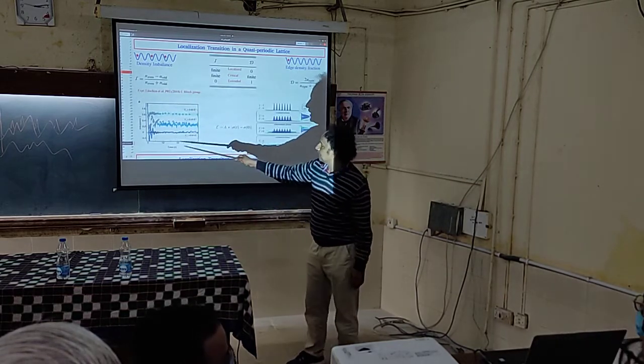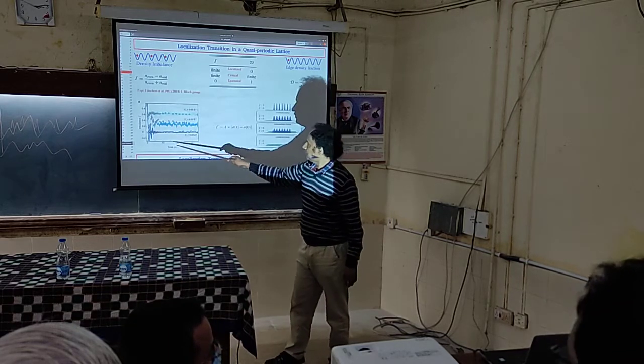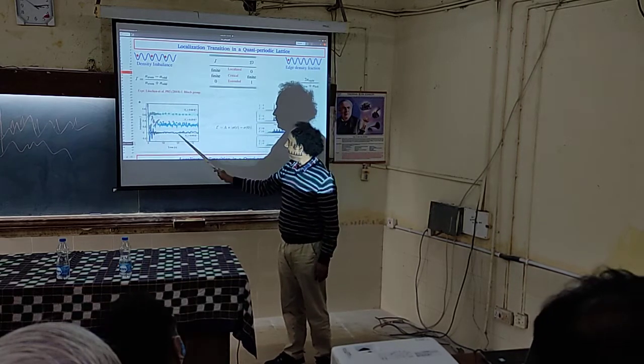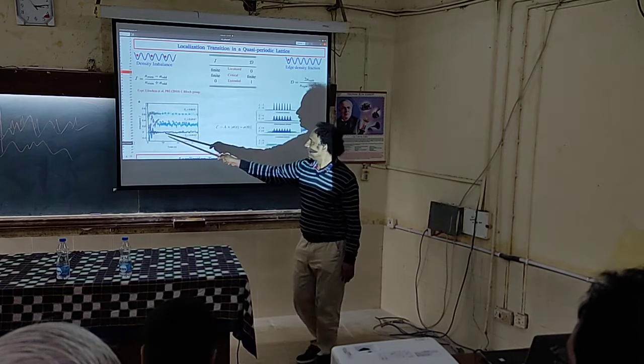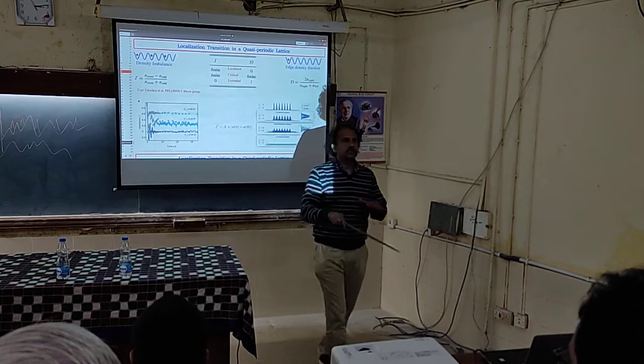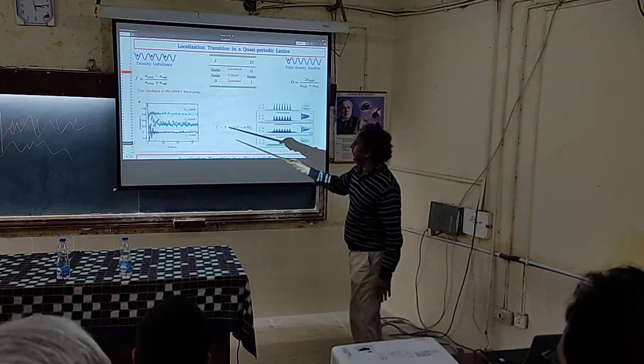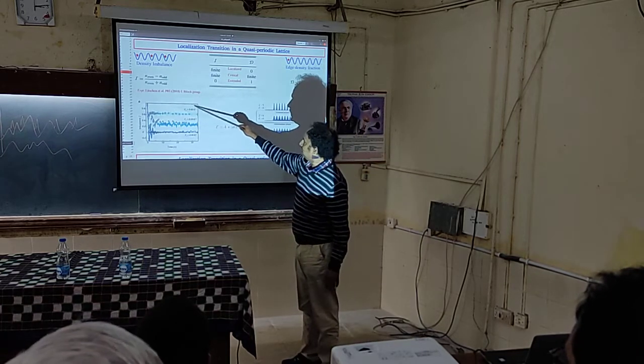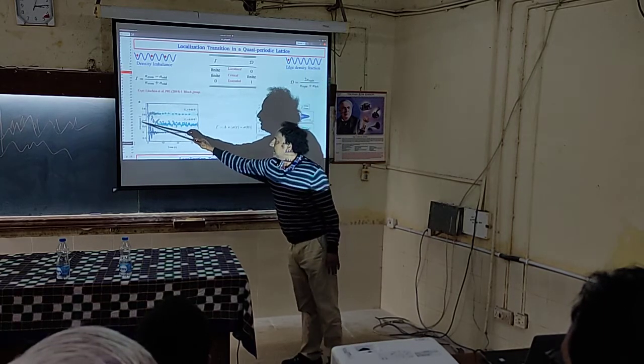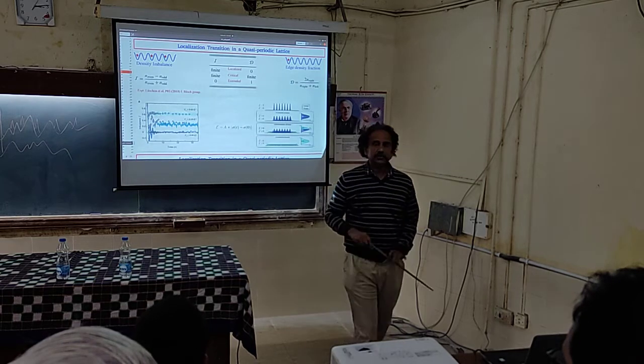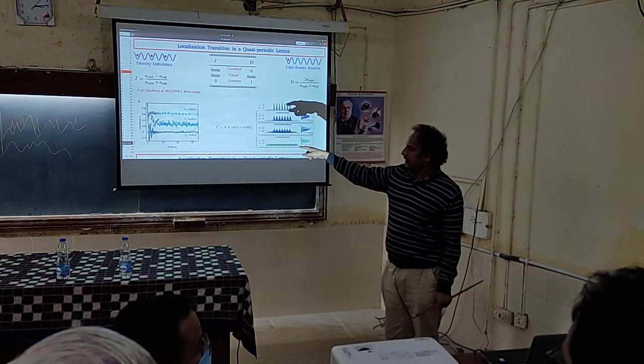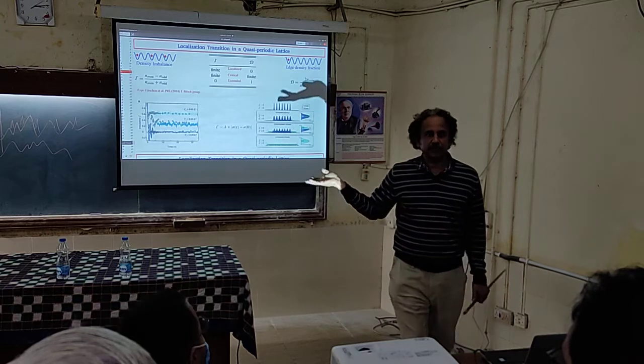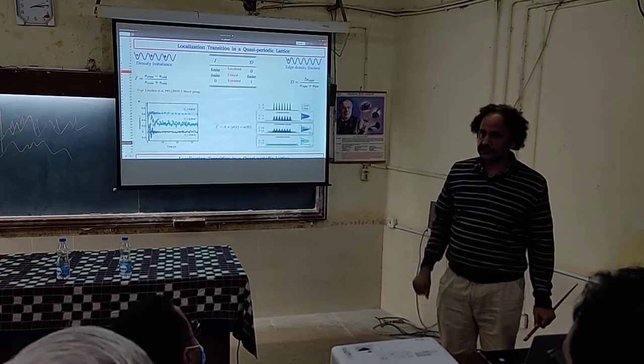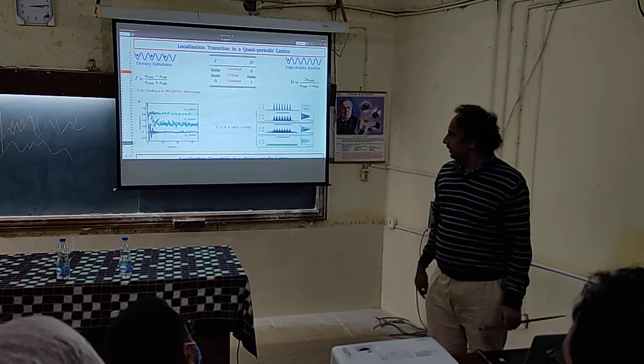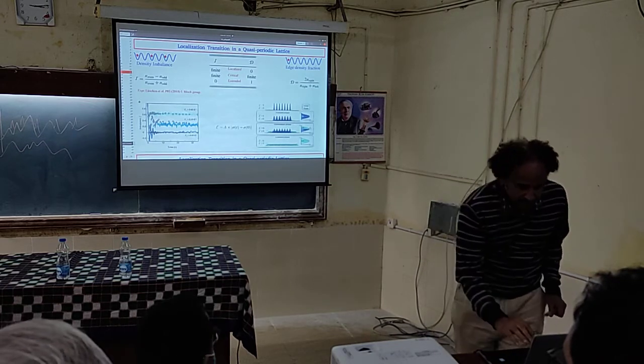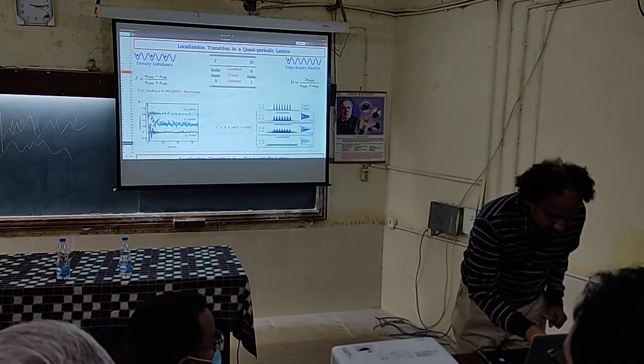So here you can see this experiment. This is the time evolution. This imbalance is plotted here. When this disorder potential is 0, then this quantity is 0. That means there is a superposition of all these single particle states. And as you increase this disorder potential, you can see that the imbalance is finite. This is a very important finding. This is the first observation of a localization transition using experiment in 1D, and it's a very important paper.